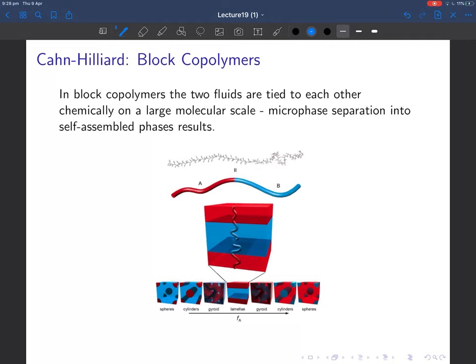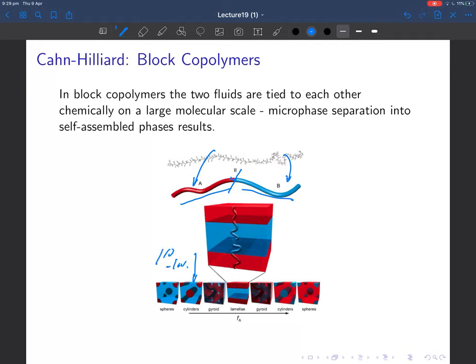There are more complicated fluids, such as fluids of block copolymers. A polymer is a long chain molecule; a block copolymer has a chain consisting of two chemically distinct species — labeled red and blue here, but could be polydimethylsiloxane and polyethylene. Polymers desperately want to phase separate from each other. However, because the two blocks are chemically joined, they can't fully phase separate — they can only undergo micro-phase separation at a scale of roughly 100 to 1000 angstroms.